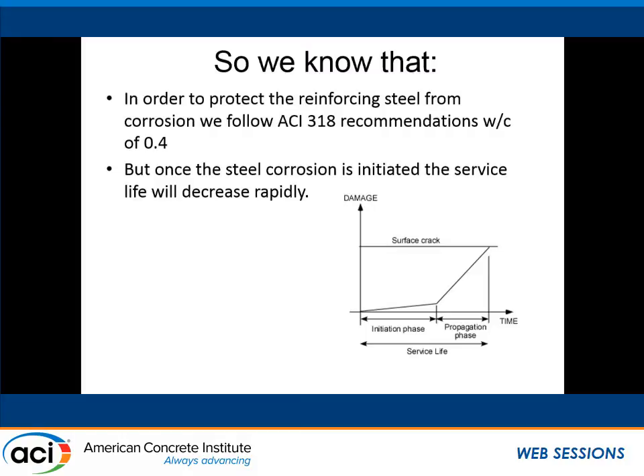This protects our steel from corrosion, but once corrosion starts, it progresses relatively rapidly. Once it initiates and starts to propagate, we get cracks, it splits open, water gets in there, or whatever, and things fall apart quickly. So we said, okay, maybe one of the theories is this has lasted so long because it hasn't split open. It's corroded in there, but we got a lot of pore space, so it's oozing into the pore space. Hey, maybe that's what we're doing.